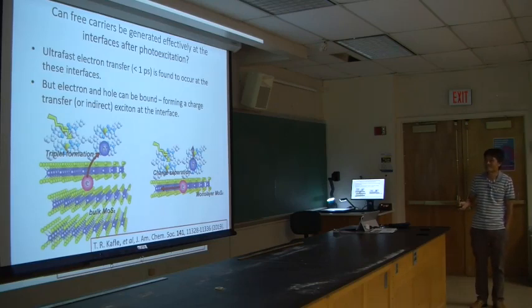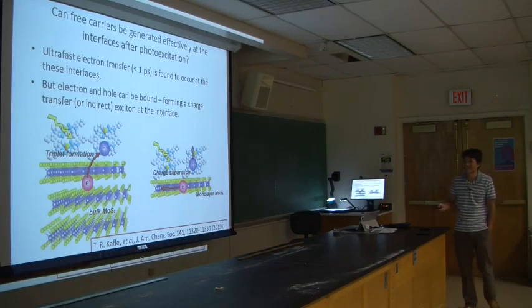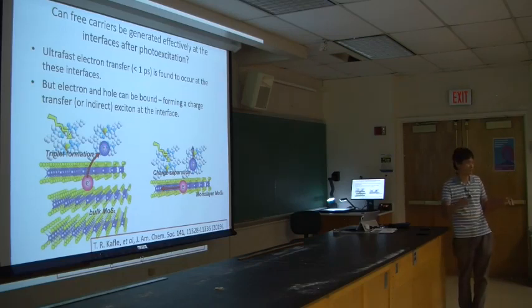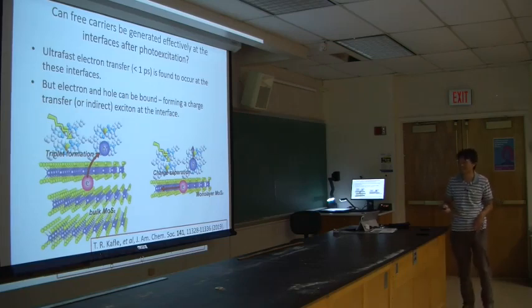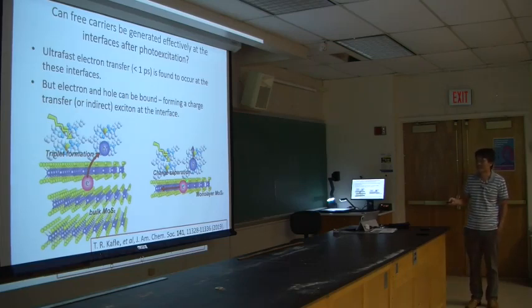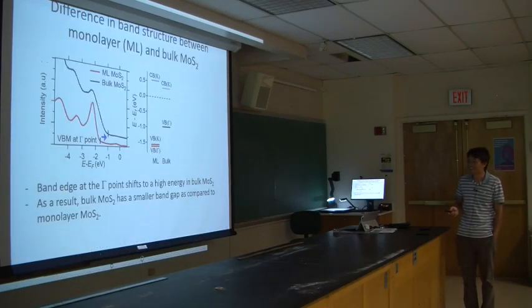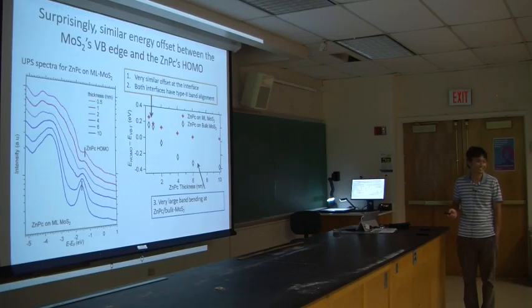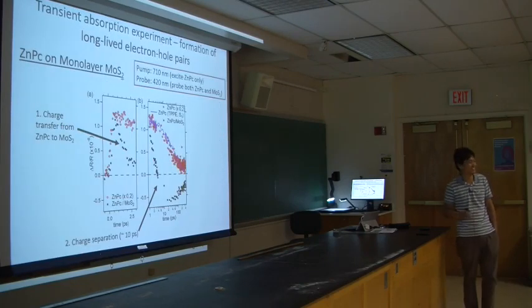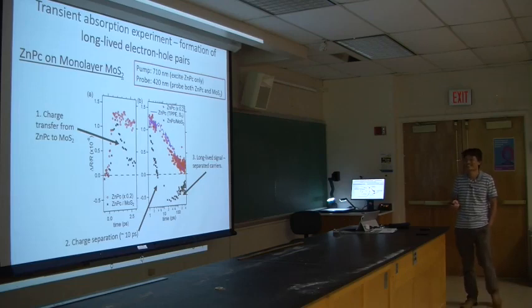So for this bulk MoS2, so basically many MoS2 layers, right? We actually don't see these charge transfer excitons separate. But instead, the electron actually goes back to the organic layer and forms these so-called triplet excitons. But for the monolayer, we see that the electron and hole actually separate at the interface. So I will skip all the experimental details if you don't mind. Just believe the conclusion here.